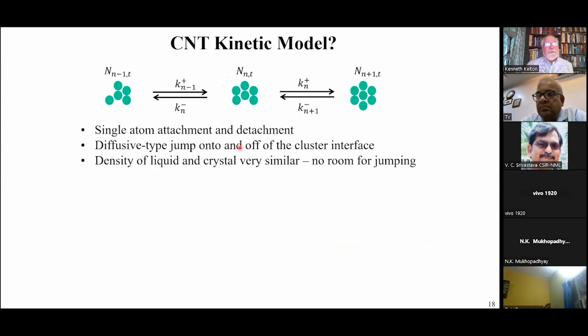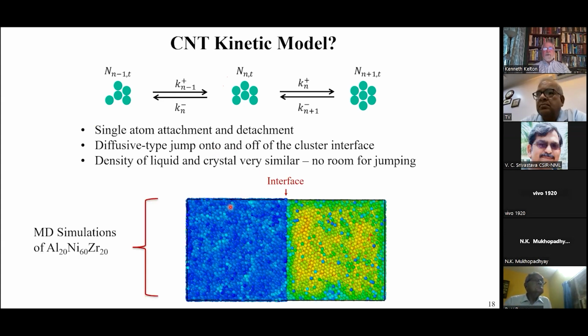Now, what about the kinetic model? The kinetic model assumed that we have single atom additions and subtractions to the clusters as they grow. I've illustrated that here in a different way. There are single atom attachments and detachments. There are diffusive type jumps onto and off of the cluster interface. But the problem is, if you look at the densities of the liquid and crystal, this is the liquid, this is the crystal in an MD simulation, there's very little room for jumping. So the idea that Turnbull and Fisher have, where you have a jump going from the liquid to the crystal, seems problematic.